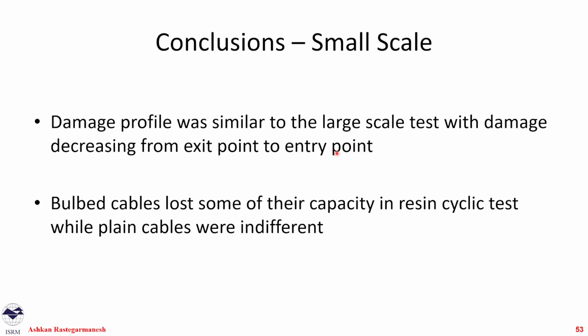We realized that the damage is very similar to large scale tests, so we get more damage towards the exit point compared to the entry point. And the bulbed cables, we realized that they lose some of their capacity in cyclic tests, while plain cables were indifferent to the cyclic and non-cyclic testing.